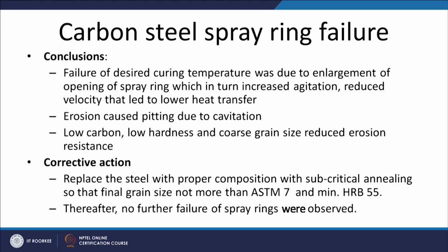The conclusion was that the failure to reach the desired curing temperature was due to the enlargement of the opening of the spray ring, which in turn increased the agitation and reduced the velocity, and that led to lower heat transfer, which in turn reduced the curing temperature. Erosion was caused in the form of pitting due to cavitation, and cavitation occurred due to the lower carbon content, lower hardness, and the coarse grain size of the ring which was subjected to the erosion. All these factors reduce the erosion resistance: low carbon, low hardness, and coarse grain size.